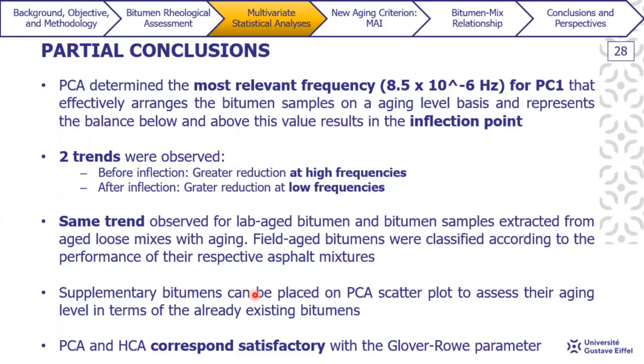PCA revealed the most relevant frequency of 8.5 times 10 to the power of minus 6 Hertz for PC1 and effectively arranged the bitumen samples on an age level basis and represent the balance below and above this value, which resulted in the inflection point. In this case, two trends were observed: before inflection, we seem to have a greater reduction at high frequencies, and after inflection, a greater reduction at low frequencies.